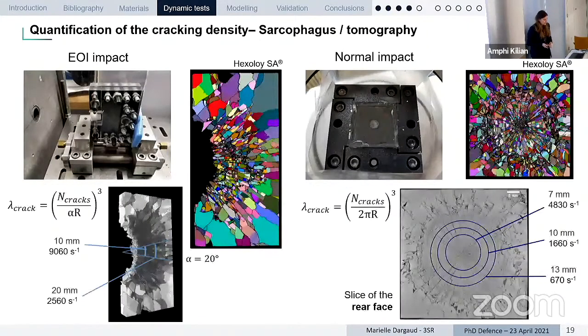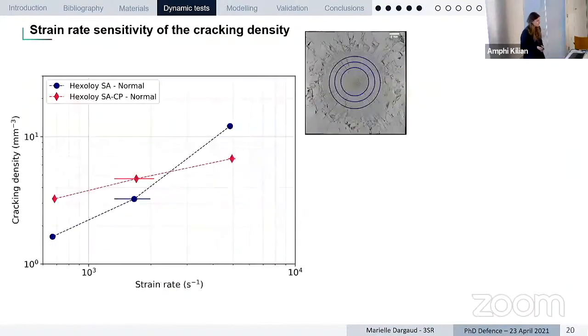For the quantification of the crack density, we took the exact same positions where we had the estimation of the strain rate from numerical simulations. We count the number of cracks that we obtain experimentally close to these positions. For the normal impact, we are just looking at the rear face of the ceramic where we generate this tensile loading. This way, we have different positions where we have an estimation of the strain rate, and we have here a quantification of the cracking density. Here you have a plot where we compare, for the two materials, the evolution of the cracking density according to the strain rate evaluated numerically.